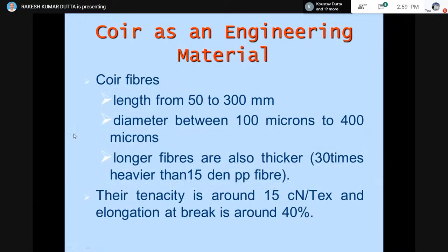Now coir as an engineering material. If you look at the coir fibers, their length varies between 50 to 300 mm, and diameter between 100 to 400 micron. Longer fibers are thicker or heavier than 15 Den PP fibers. 15 Den is basically a textile unit. Their tenacity is around 15 centinewton per tex.